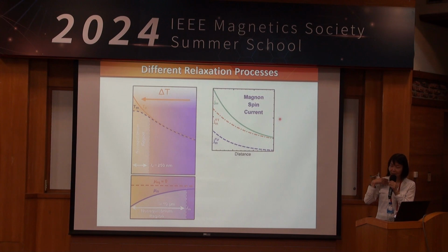That, to me, is difficult, because you're counting on the interface being reliably repeated in different labs, and that's often not the case. Right? So here, using light, I can actually do a measurement of spin transport and energy transport in the insulator itself. This is where light scattering really has an advantage: measuring insulators. So I don't rely on any spin transfer to a heavy metal layer to quantify that way.